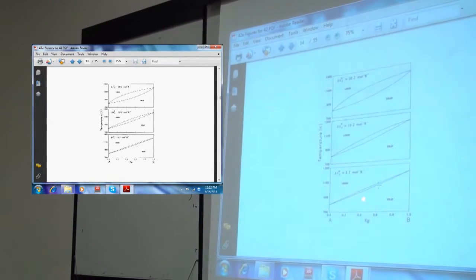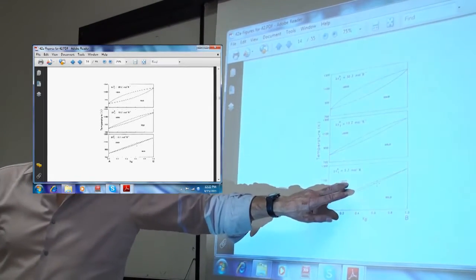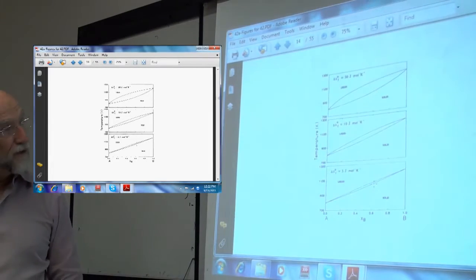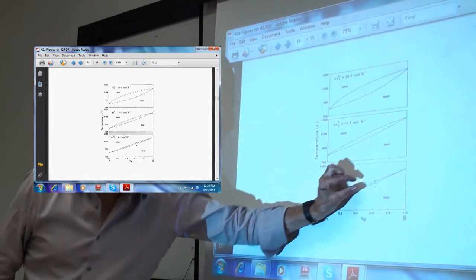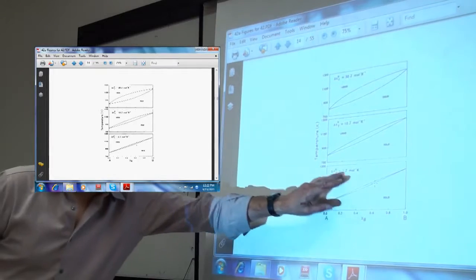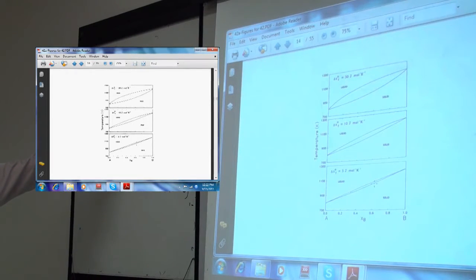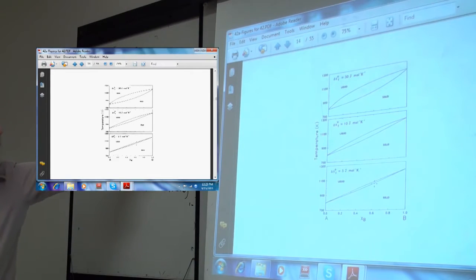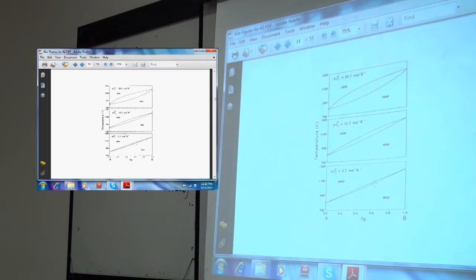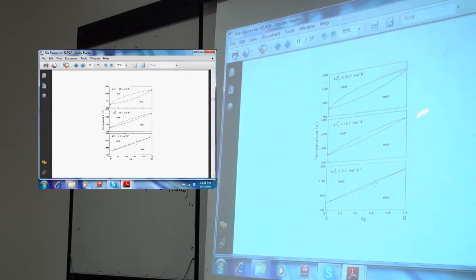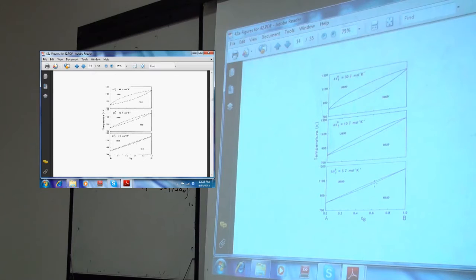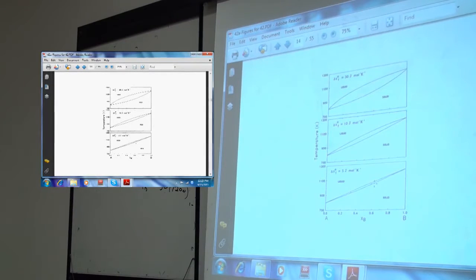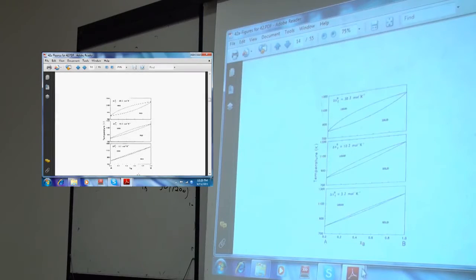Now, you'll see two-phase regions like this between two solid allotropes. So this is the body-centered and this is the face-centered. Between two allotropes, two different solid-state structures, you tend to find extremely narrow two-phase regions. That's because now we're going from alpha to beta, and this is delta G of the alpha-beta transformation. The entropy of solid-state transformations tends to be about 10 times less than that of the solid-liquid, because the entropy change is so much smaller, with not much change in disorder as you go from one structure to another. So solid-solid phase diagrams tend to have very narrow two-phase regions, solid-liquid wider, liquid-gas wider. If you have a really big number of atoms per mole, it also tends to be wider. That's the fundamental reason.